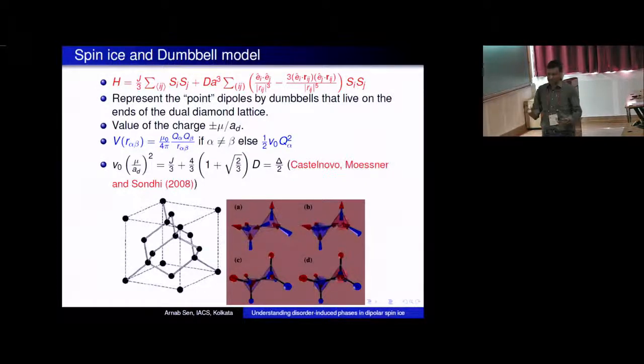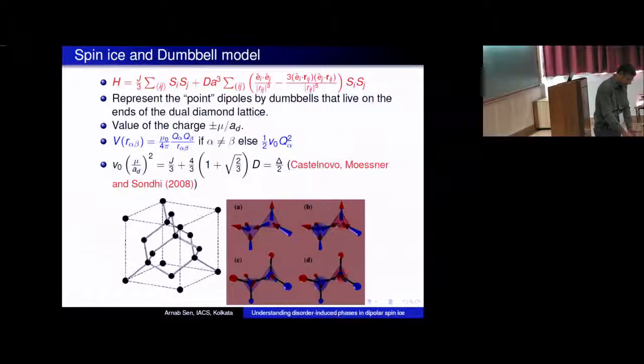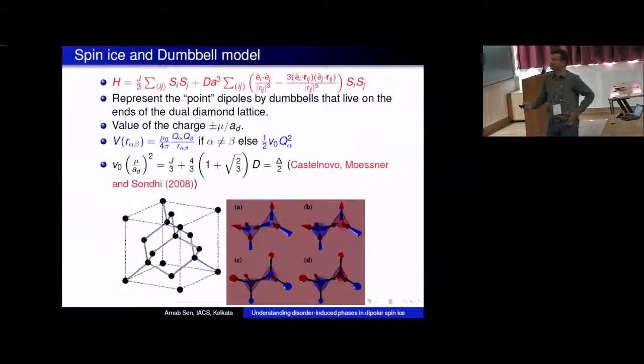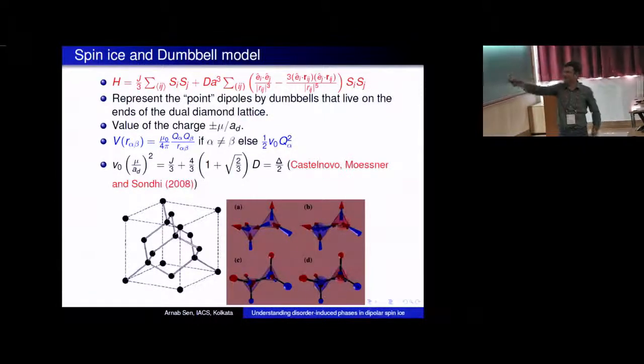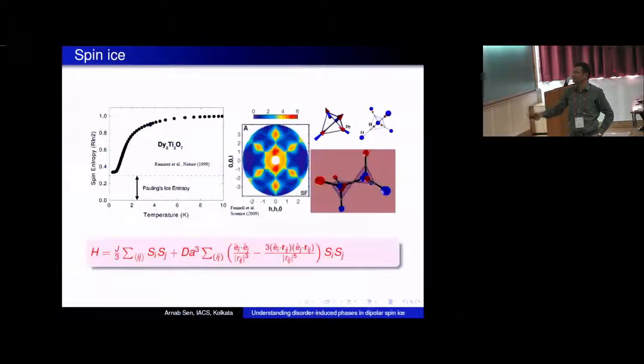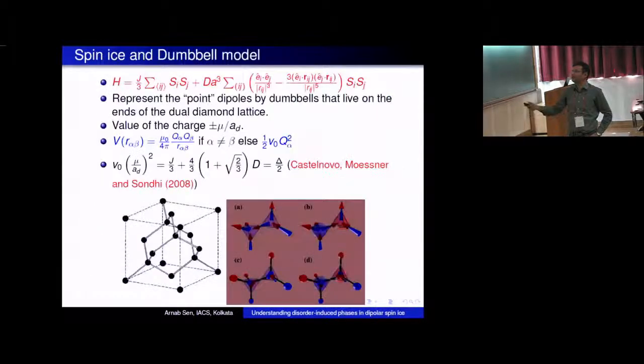And you can furthermore show, for example, you could do a simulation or try to do some rough back-of-the-envelope calculations, but some people actually did the hard simulations. You can actually show that if you keep decreasing V naught, ultimately there's a phase transition to some other kind of a ground state where these Q alphas are not all 0. But thankfully, all these spin ice compounds that I talked about actually lie on the other side, where you are in the simple ground state manifold, which is also the ground state manifold of the nearest neighbor model. So this explains why this long-range model and this slightly tweaked model have identical ground states to the short range model. Okay, so that's point one.